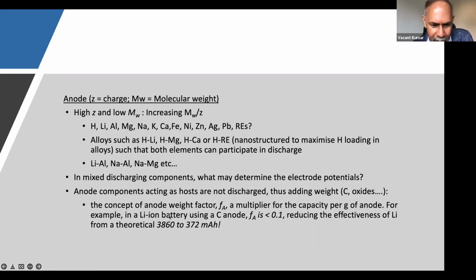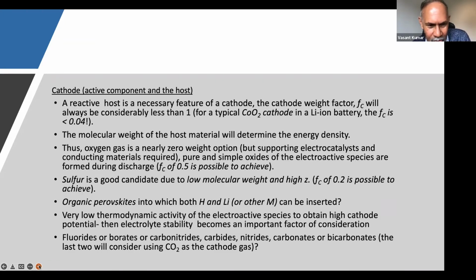So take a lithium-ion battery. Lithium itself has a capacity of 3,860 milliamp hour per gram, and that is a theoretical capacity. But as soon as we use carbon, the multiplier is less than 0.1. It reduces to 372 milliamp hour, but keeps the battery safe. So therefore, it will be very attractive if somehow we find a safe way of using lithium. Needless to say, a tremendous amount of work is going on to do that at the moment.